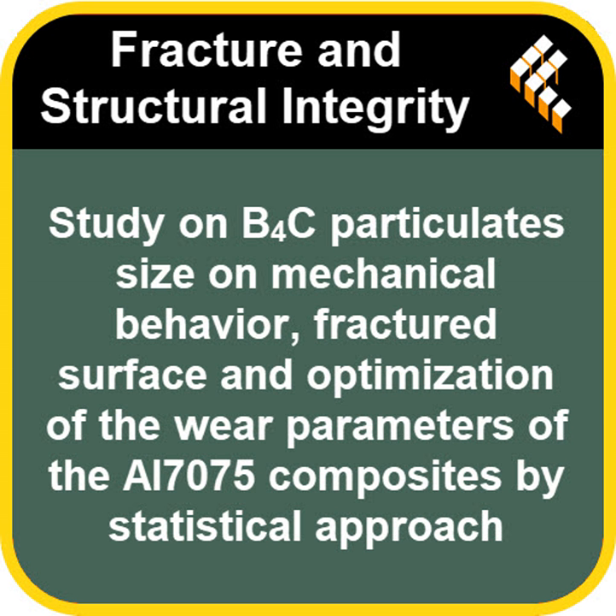The larger microparticles tend to create more noticeable bumps or asperities on the surface. That means more points of contact, more interlocking, hence higher friction. The smaller nanoparticles embed more uniformly, they don't stick out as much, leading to better load distribution across the surface and just fundamentally lower friction. Smoother sliding, less energy lost.